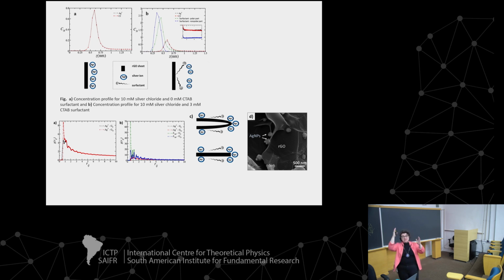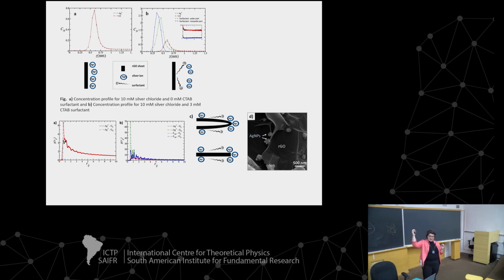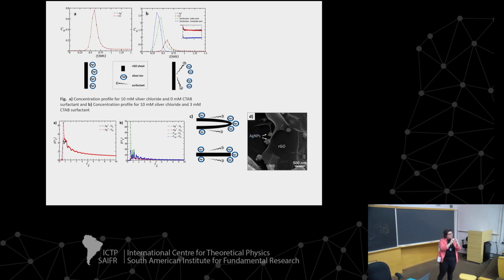The surfactant interacts first with the graphene sheets, hindering the addition of the nanoparticles. And the consumption of this surfactant avoids the control of the size of the nanoparticles. There's a competition between the graphene and the nanoparticles for the surfactant. So we have materials with bigger nanoparticles. And when we insert first the precursor, the ions from silver, we can form nanoparticles, mainly in these wrinkles, these regions, because of the interaction energy we have in these wrinkles, and we have smaller and well-controlled, well-positioned nanoparticles.